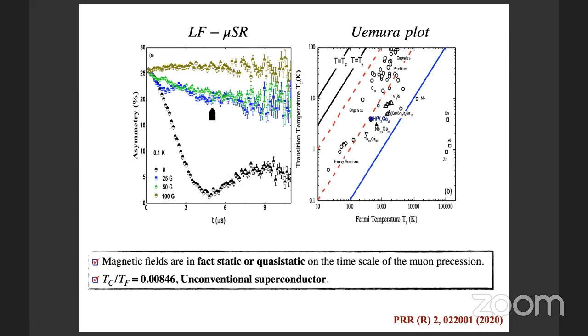In case of magnetic impurity present in the system, or in case of a magnetically ordered system, we generally observe a drop in the asymmetry and a very large internal field. In this case, the internal field is below, I think, 50 Gauss.